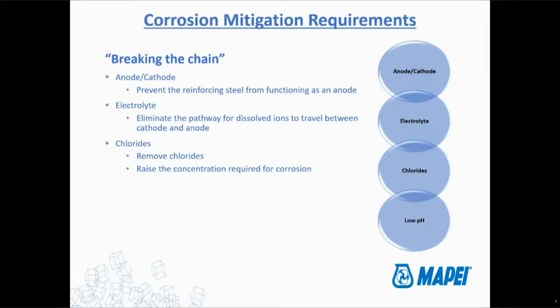And then the other thing that you can also do is just raise the concentration required for corrosion. So remember, we said there was that parts per million, about 330 parts per million, the chloride concentration limit for the passivation layer. What we can actually do is add materials to the concrete mix or the repair mix that raises that concentration. So we can get up to, say, maybe 500 or 600 parts per million and just delay the process a little further. Now, that also assumes, of course, that you're keeping the pH above 10, because we said also if you get below that 10 and a half, the chloride will also start to react. So it's just a belt and suspenders, slow-you-down type approach, but not a permanent fix.